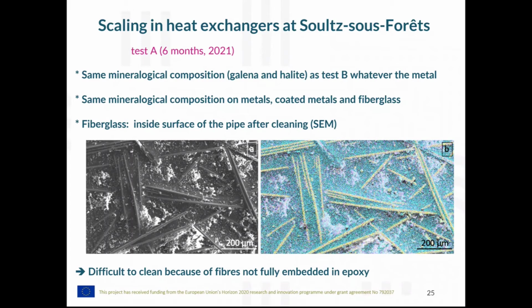And when we have a look at the right part of the figure, in yellow are the glass fibers. This is silica, which appears. In blue, it is the epoxy, and in white, it is the scales composed of lead and sulfur. So it appears to be difficult to clean the fiberglass because of the fibers, which are not fully embedded in epoxy. Next, please.